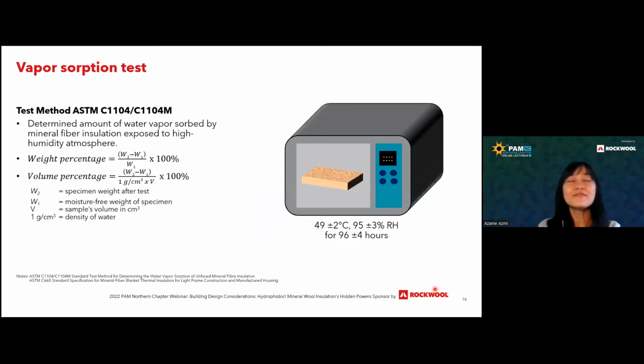The fourth one that I mentioned is the vapor absorption test, which is ASTM C1104, C1104M. How you do the test is, look at the picture here on the right, you put the sample in the oven and heat up to 49 degrees C at 95% RH, which is very, very high, for 96 hours. So you want to see whether that insulation will absorb this high humidity. And from there, they check the weight either in percentage or in volume percentage.